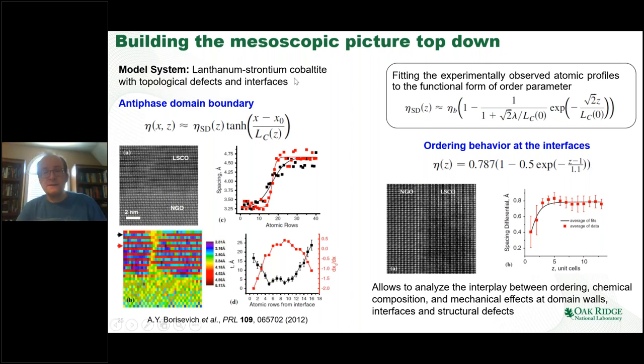So the pathway in this case is very simple. We just have the free energy. We calculate the solution, for example, for order parameter across the interface. This solution will have some constants, which we normally don't know. So we just have an unknown parameter. However, if we take the atomically resolved data and we fit the atomic distortions that we see in electron microscope to our macroscopic solution, we can derive the value of these constants.